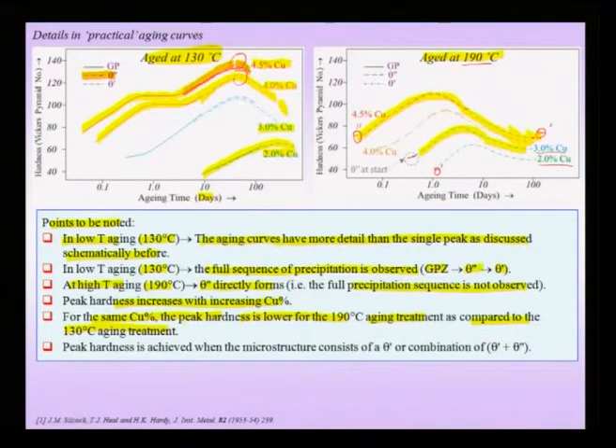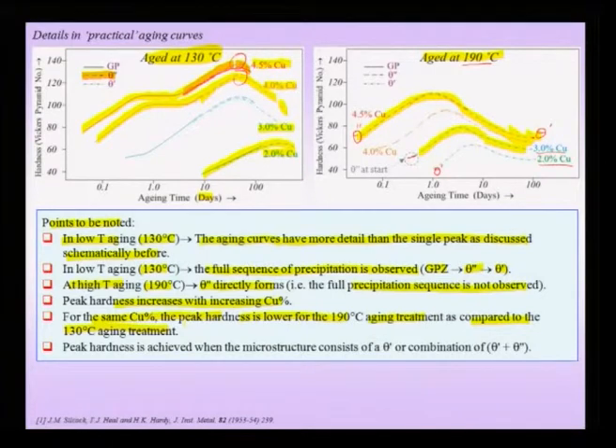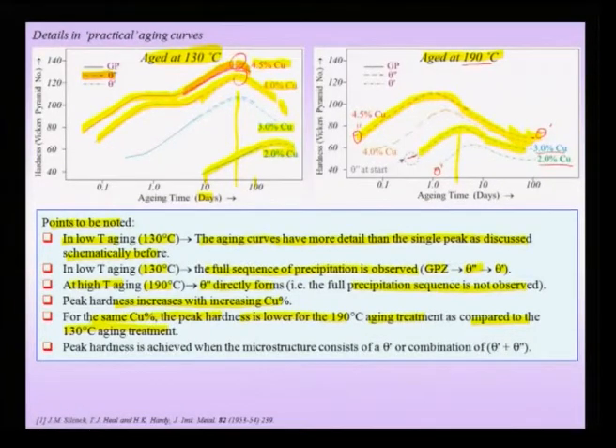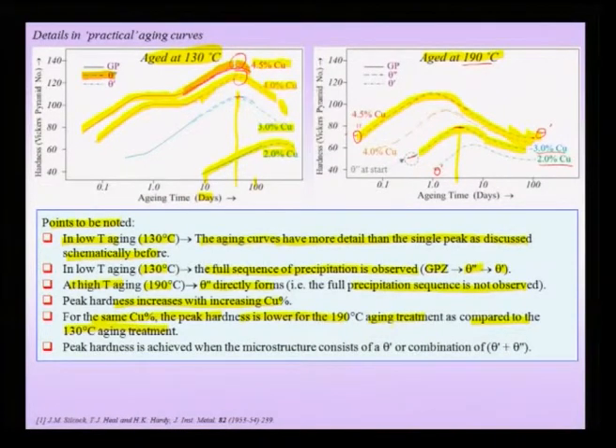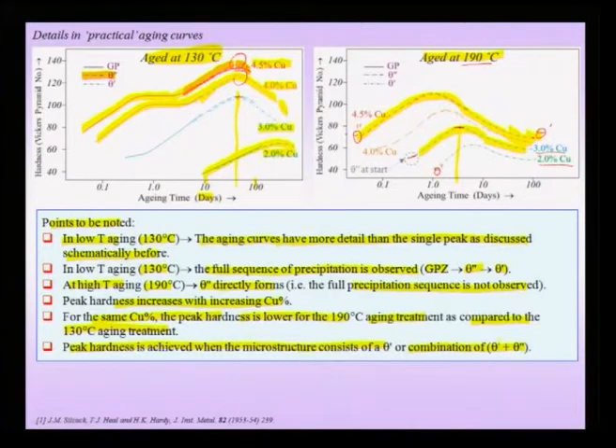For the same copper percentage, it is better to age at lower temperature to get higher peak hardness, but we have to wait longer — for 3% copper at 130°C, peak hardness is reached between about 10 and 100 days, while at 190°C peak hardness arrives in less than 10 days but at a lower value (e.g., ~70 VPN versus ~100 VPN). The peak hardness is achieved when the microstructure consists of theta prime or a combination of theta prime plus theta double prime.